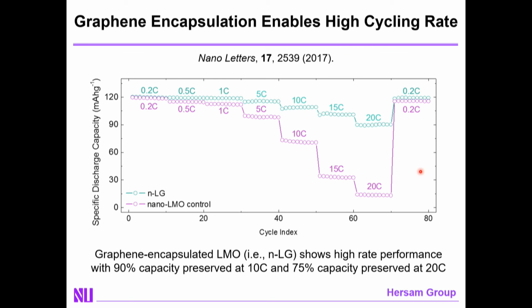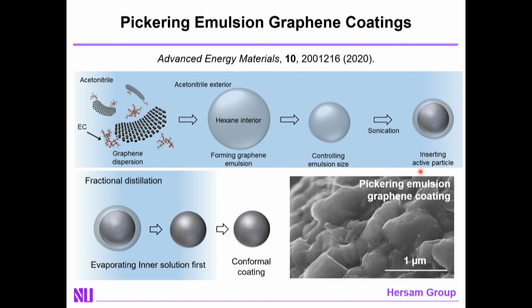The issue, though, is that the way in which we did this initially is that we were just mixing together graphene and the cathode particle. And as a result, to make sure you got coating on the surface of every single cathode particle, you had to put in a lot of extra graphene. That is, of course, not great, because graphene is just dead weight in the battery. And obviously, you'd want to minimize the amount of dead weight that's present. And as a result, we had to come up with a much more efficient way of getting the conformal coating on the surface of the cathode particles.